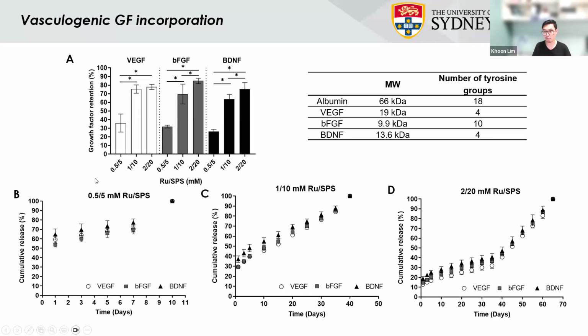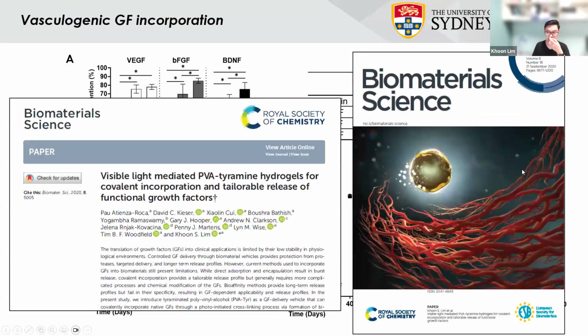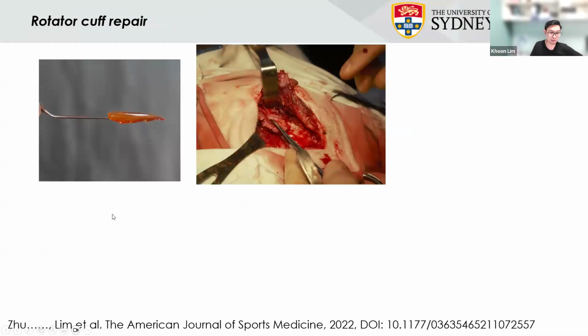And by playing around with the degree of cross-linking, we can now tune the degradation or the release profile of these growth factors that we put in there. So we thought this was really interesting, and we did publish this work too. Now, we were looking at translational application.